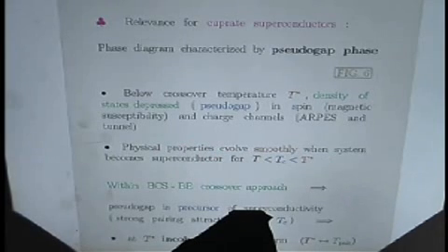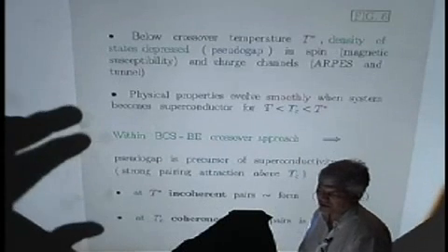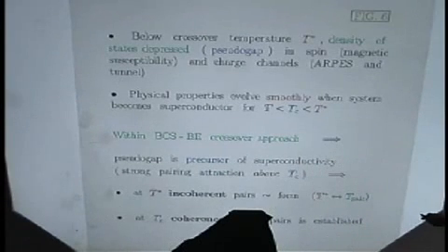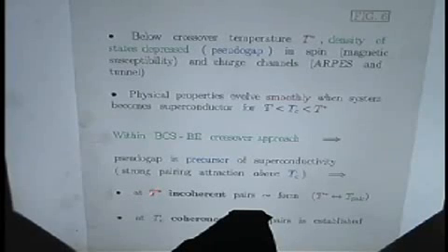Now, within this sort of crossover approach that I was describing, the pseudo-gap is understood as a precursor of superconductivity, because you get strong pairing not only below TC but also above TC in this new phase that I was describing. And essentially at T star, incoherent pairs or almost bound pairs start to form, and you identify therefore T star with a pair temperature, whereas at TC, the coherence among these pairs is established.